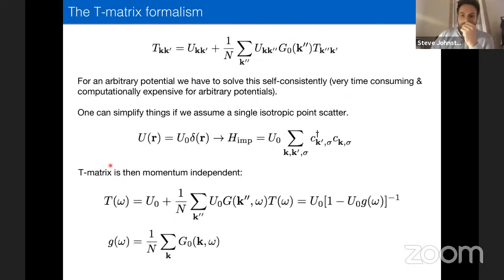To simplify matters, this T matrix equation that I've written down here, there's many momentum arguments. And if you've worked with this equation before, you know that this can be quite challenging for an arbitrary impurity potential to actually evaluate. So we make a bunch of standard approximations. The main one being that I'm going to treat the impurity potential as a delta function. This effectively removes the momentum dependence of the impurity potential. And then if you do that, you can convince yourself that this T matrix actually becomes momentum independent, and you can just have a closed form solution, which is related to this momentum averaged Green's function, a non-interacting Green's function here. So this simplifies the algebra considerably. And so this is the approach that I'm going to be using in the simulations that I'll show you later.